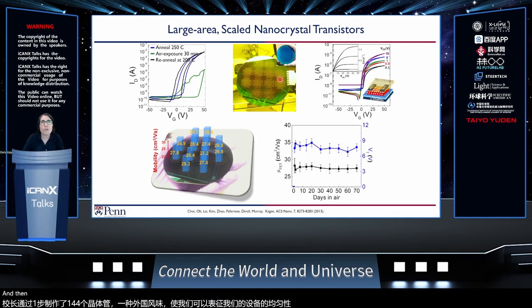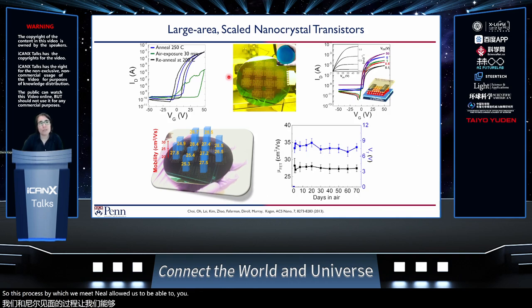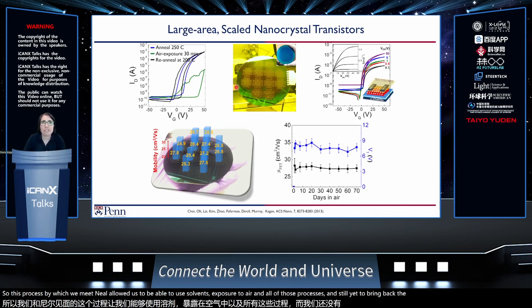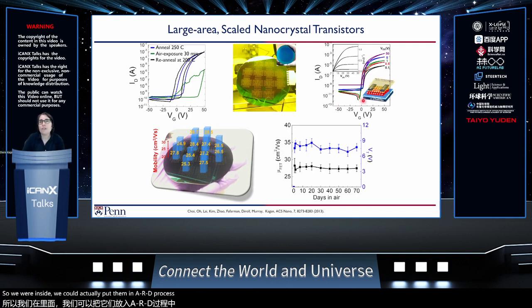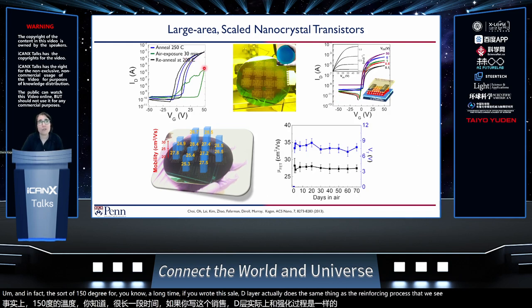The other thing that is important is that we did this by using photolithography. This process by which we re-anneal allowed us to use solvents and expose it to air, all of those processes, and still bring back the characteristics. And then we could take these wafers and put them in an ALD process and encapsulate them. This is an example where we encapsulate them with aluminum oxide. And in fact, the heating at 100 to 150 degrees for a long time as you grow this ALD layer actually does the same thing as the re-annealing process. So you don't have to do it separately. It happens during this encapsulation process.